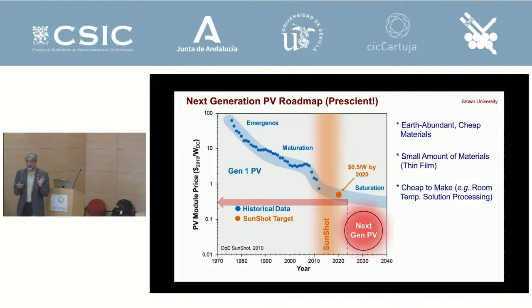And so if you make solar cells at near room temperature, you're winning the game. You're reducing the amount of energy you need to make the renewable energy devices, which is very important. And then, as I mentioned, small carbon footprint. And the efficiency has to be high. Because if you look at the Shockley-Queisser limit for a single junction solar cell, the theoretical limit, the absolute theoretical limit by physics, is 33%. The solar cells that you can buy, the best ones are about 25%, regular ones are about 20 to 21% efficient. Yes, solar energy is free, but then you have to use a large area in the world in order to collect that energy and convert it into electricity, correct?